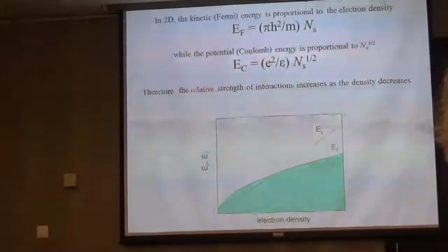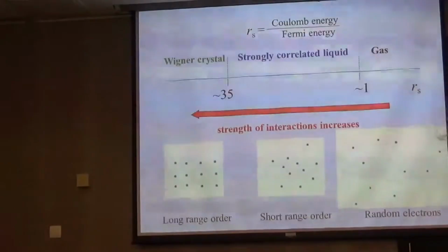So suppose I want to characterize the relative strength of interactions by this dimensionless parameter, R sub s. It's simply a ratio between Coulomb energy and Fermi energy. So this ratio is proportional to the inverse square root of electron density. The lower the density of electrons, where density is the number of electrons per square centimeter. Right? It's a two-dimensional system, so it's square centimeters, not cubic centimeters.